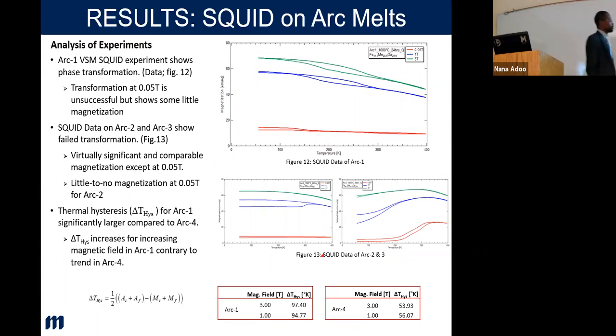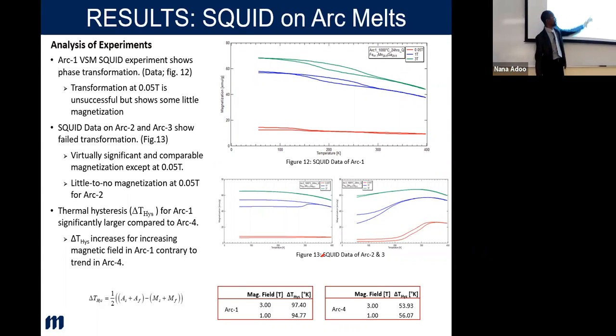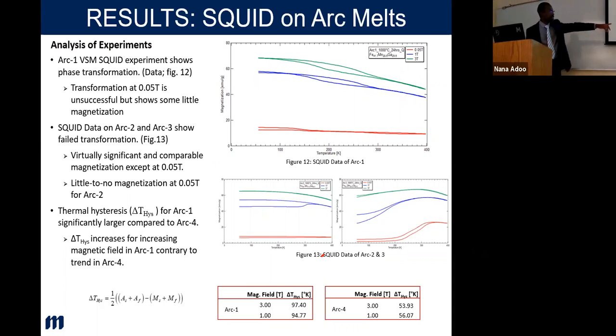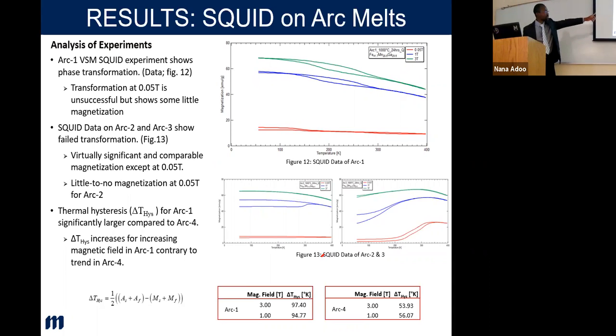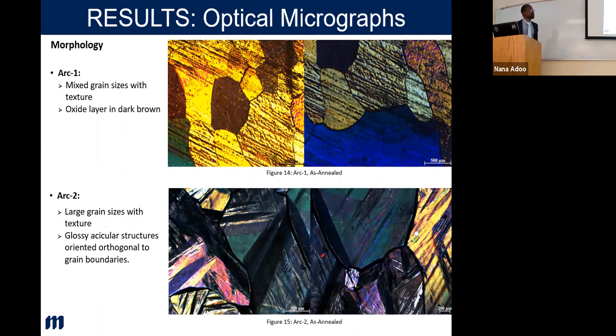For this, which was the one that succeeded, which is the first one, I'm measuring around 90, which is matching with literature. And then the others which failed, the other which I previously measured was around the 50s, which is the second one, the fourth one, this one. I looked at why some of these materials transformed and then some did not transform. And by that, you would have to look at the micrographs. And to look at that, I started with